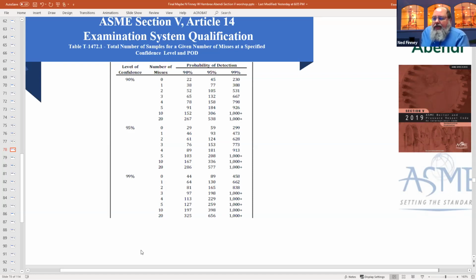And one of our major rewrites is to expand this, and our expansion is going to be allowing 50% confidence in finding 50% of the flaws, and then the numbers all the way up to this current 99.99. So we would have 50, 55, 60, 65, all the way through. It's quite an endeavor. The NIST, National Institute of Standards and Technology, is working with us, developing the analytics on this. We know it won't make the 2021 edition. It probably will not make the 2023 edition, but we do expect the 2025 edition to have this fully expanded level of confidence and probability of detection.